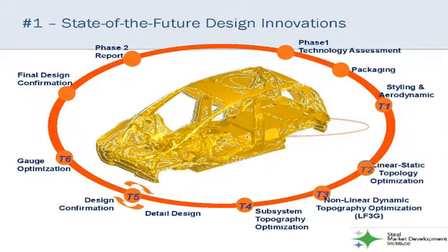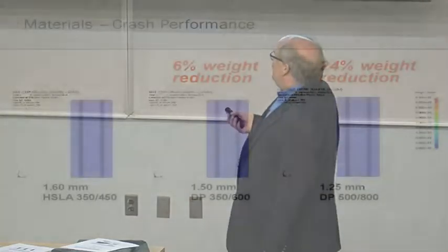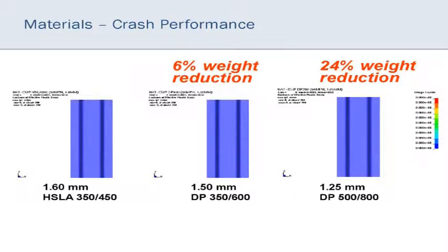And if you look at the vehicle, that's where crash energy management happens. That's what's important. That structure is what your vehicle should look like if you didn't have to keep rain out of it. But to meet the safety requirements of the vehicle, that's what your vehicle could look like and meet all the crash requirements. This shows some of the work that's been done on these steels and the fact that you can get weight reduction by going from a 1.6 high-strength low alloy, you have to remember how far it deformed because I've made it disappear, to the dual phase 600, that's a 6% weight reduction and deforms just as much, to the dual phase 500/800 with a 24% weight reduction.